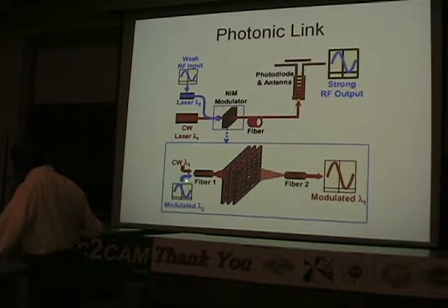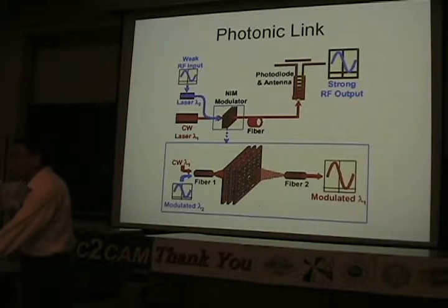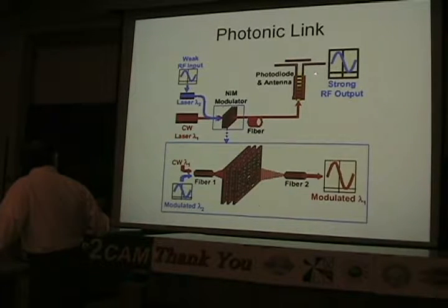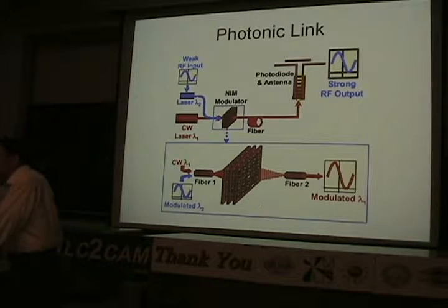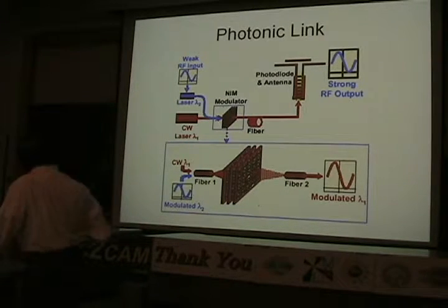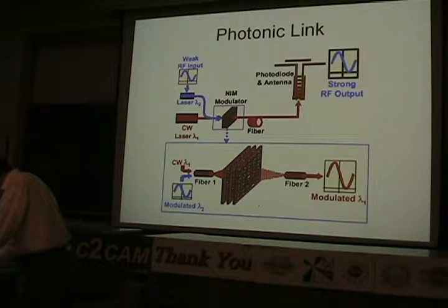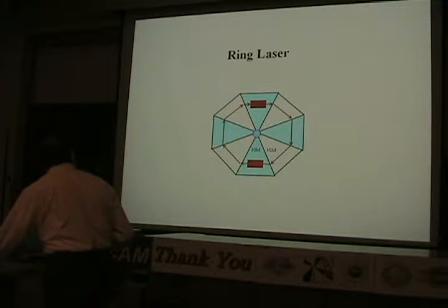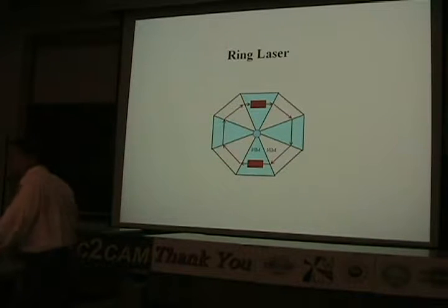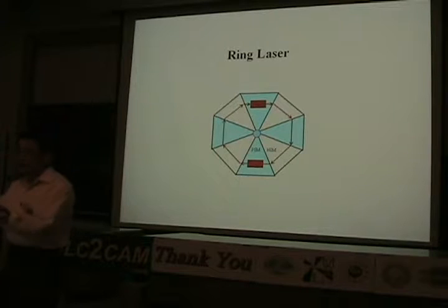On the other hand, you can also modulate, put in a weak RF input, and that will modulate this delta N here. And after the modulation, of course, you will have essentially the optical switching or modulation of the output through the induced delta N, and the output then has a strong modulation of RF on it. So that's a way to transmit a strong RF power signal. So that again has some special uses for maybe military purposes. We can make a laser easily, a ring laser easily. We just combine the negative index and positive index section-wise.